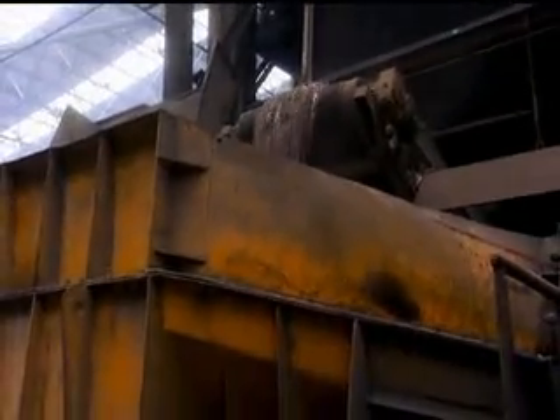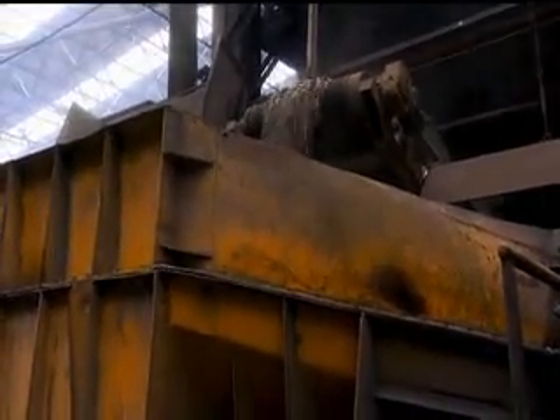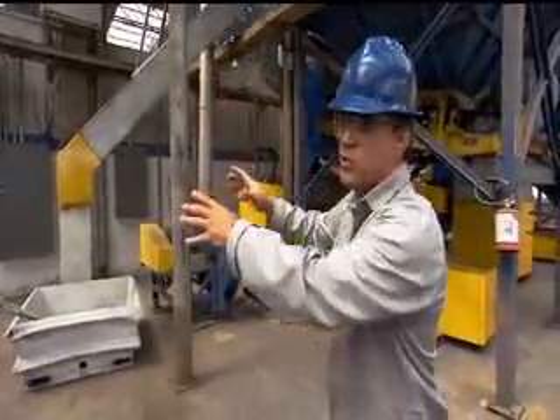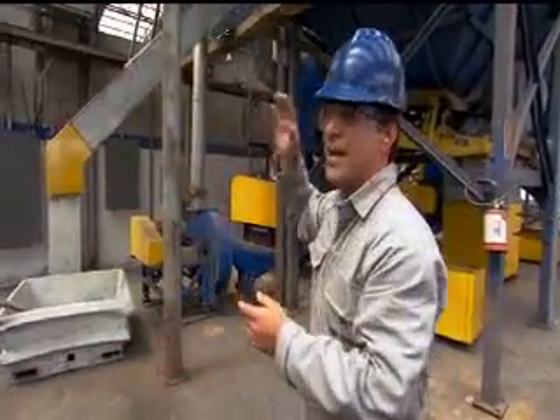You use about 7 tons of cans to make around 6.3 tons of metal. It's a violent process. The raw aluminum shreds into pieces the size of a potato chip, then onto a separator to remove all traces of other metals. Then the cans are sent pneumatically through tubes to the stocking silos, where they will be taken and thrown into the furnace.